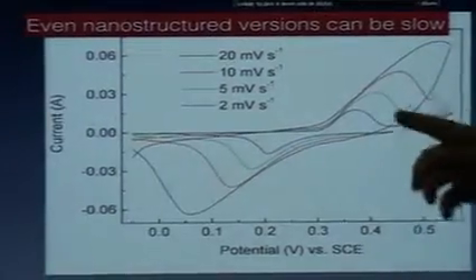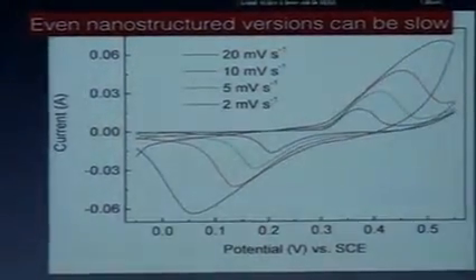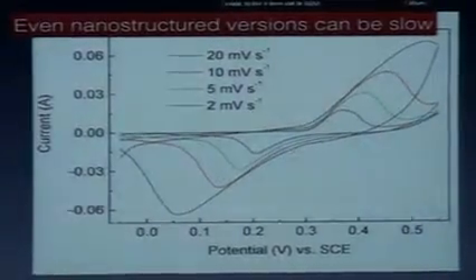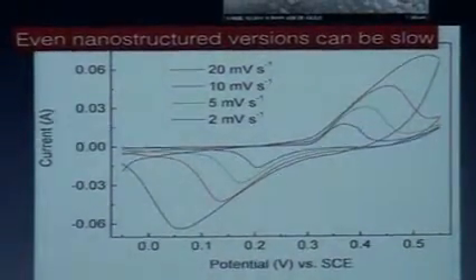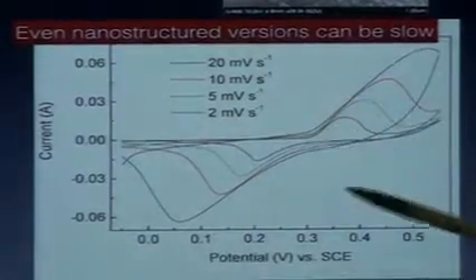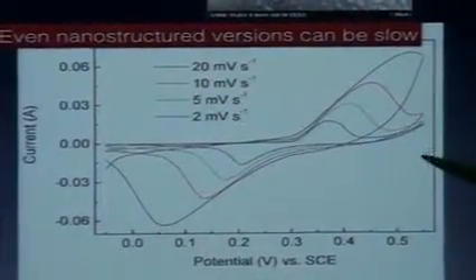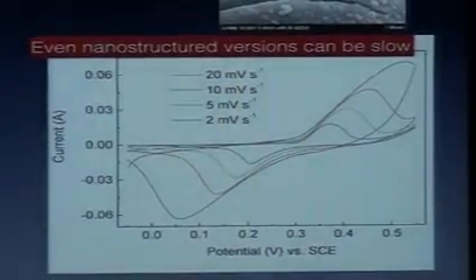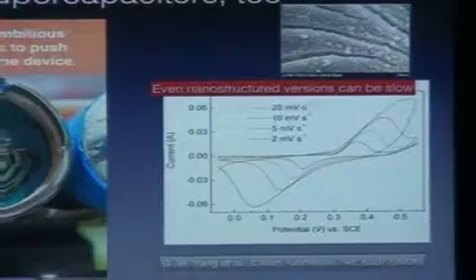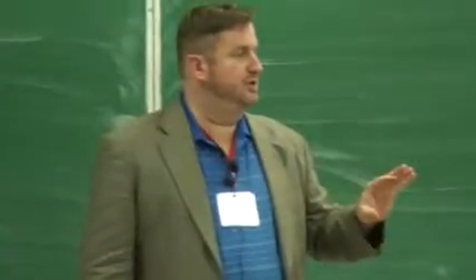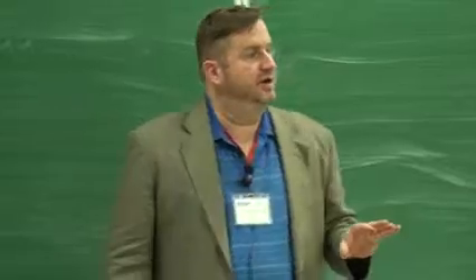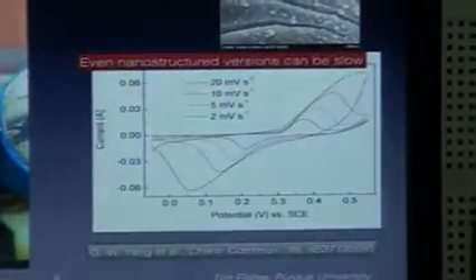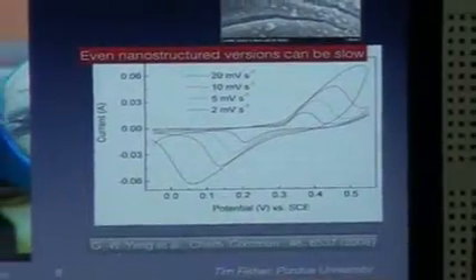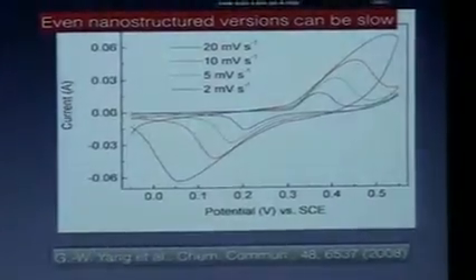You have the bird's beak type of curve for 3 of the 4 samples. But then in this case they went from 10 millivolts per second to 20, you actually start to shave off the beak of the bird, right? That's when you start to know that you're having some potentially irreversible reactions happening, or your system is just not fast enough to respond. Okay, when that happens, then instead of putting that energy into charge storage, the energy is going into a heating effect in general. Could be some irreversible chemical reaction as well.